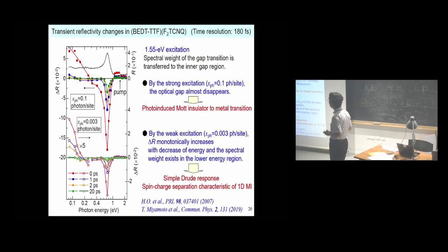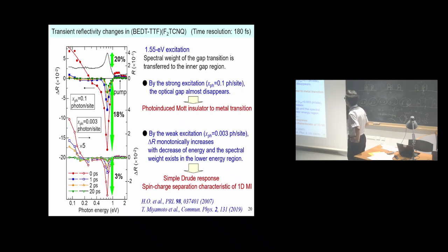In this figure, the solid line shows the original reflectivity spectrum, and color marks show the photoinduced reflectivity changes, delta R, by the 1.55 eV excitation. The upper part shows a strong excitation case with the excitation photon density of 0.1 photon per site, and the lower panel shows the weak excitation case with 0.003 photon per site. In both cases, spectral weight of the gap transition is transferred to the inner gap region. By the strong excitation, the decrease of the reflectivity reaches 18%, which is comparable to the original reflectivity peak. So, the optical gap almost disappears and photo-induced Mott transition occurs.